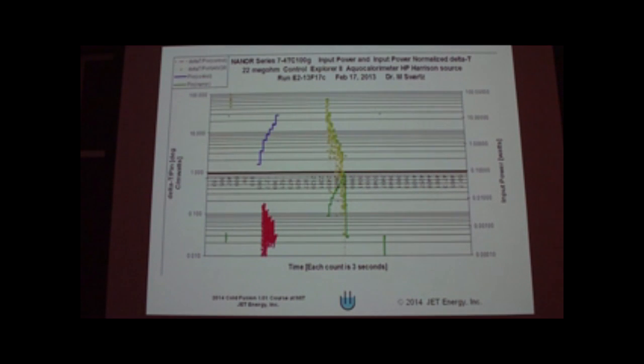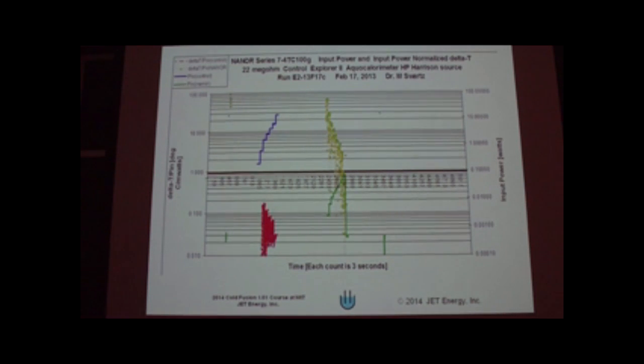In your highest power gain experience, is the high power gain essentially because you reach the same power level with much less input? Or would you more say, with the same input, I'm reaching much higher output? As a matter of fact, I think you are right on. I think we not only have issues of loading, of secondary reactions, but there may be a limit to how much power we get out of these devices. And we may be swamping them. And what we may be seeing here is, in the very low levels, the maximum amount they can put out.